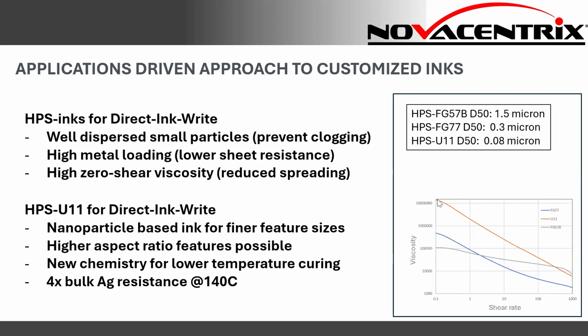You can see the zero shear viscosity is a lot higher. So that means it allows higher aspect ratios. And besides that, there are also some changes in the chemistry that we have done that allows for a much higher conductivity at lower temperature curing. For example, you can get around a quarter of the bulk silver conductivity at 140 C. So all of those make this ink a very good choice for the direct inkwrite process.